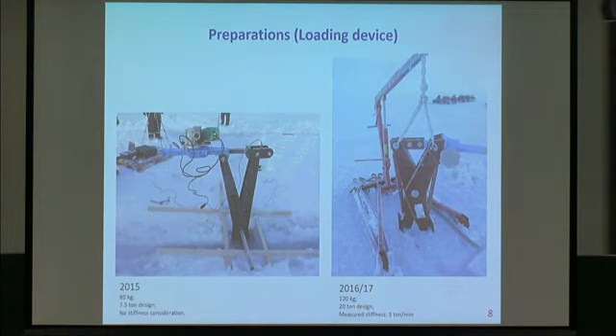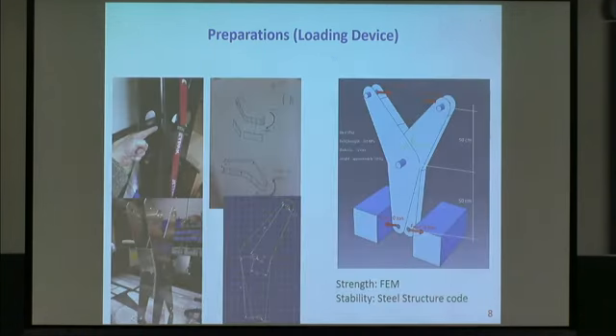So if we look at this jack, 2 plates, 200 millimeter high and 150 wide, jack working here, and also a load cell, so we could just easily lower this into the ice and start the experiment. It's also a matter of time. If you have an experiment which lasts very long or a slow procedure, you will definitely, after cutting the notch and preparing for the experiment, affect the temperature in the test area you are aiming to test.